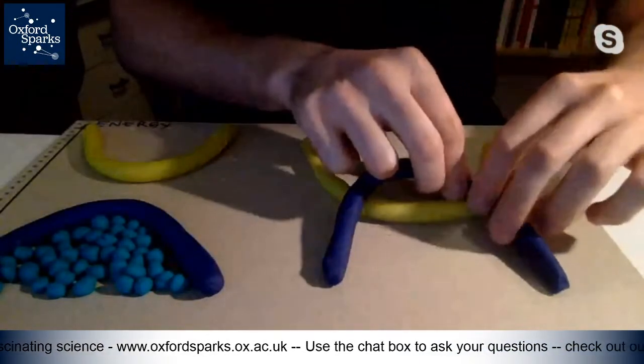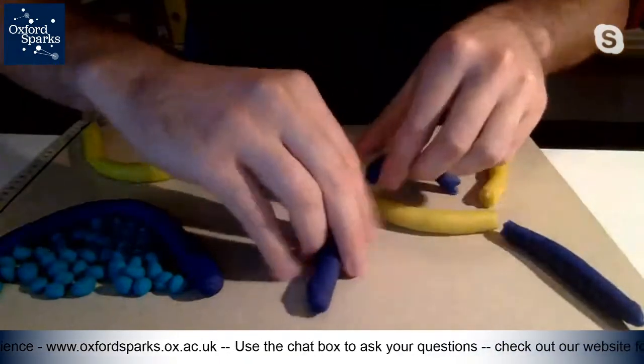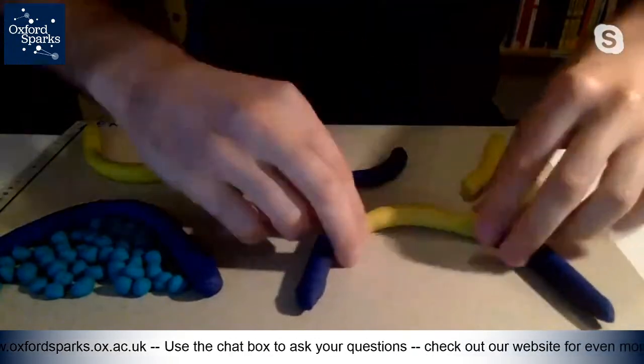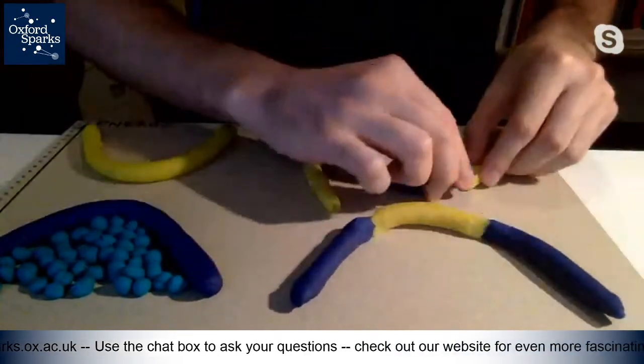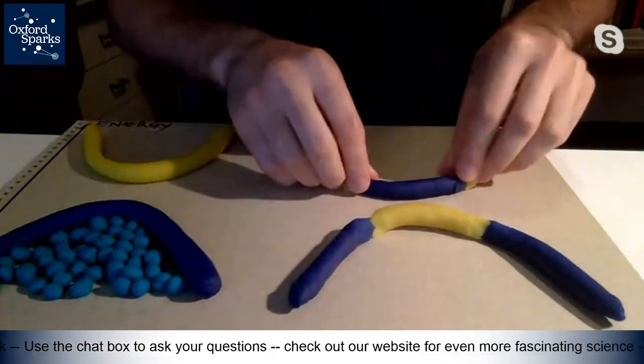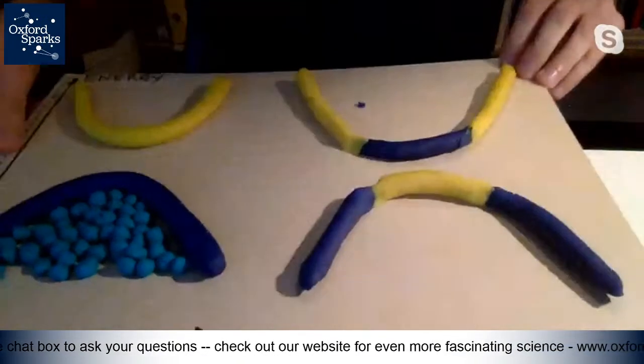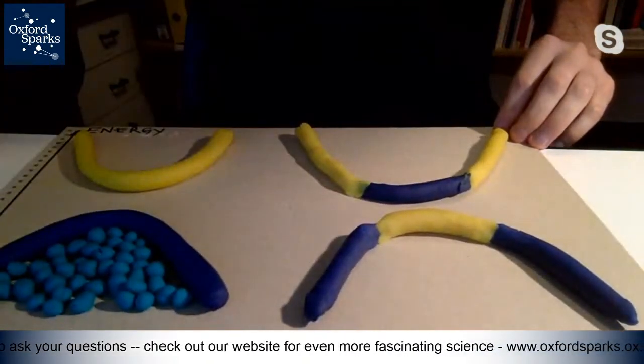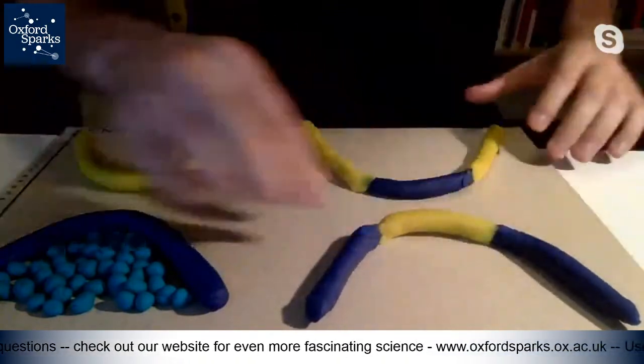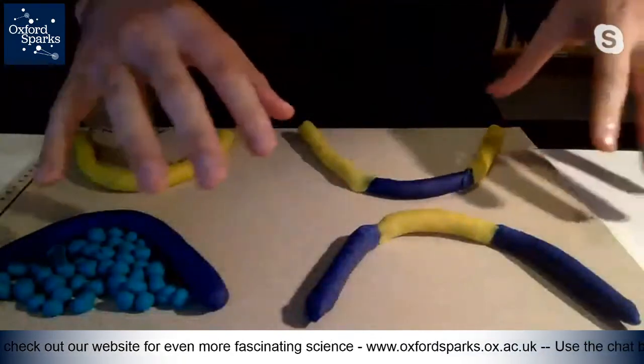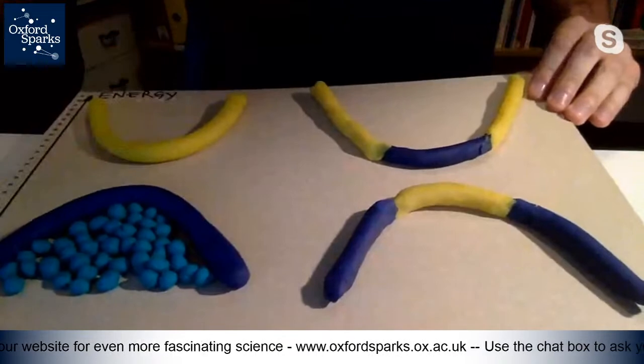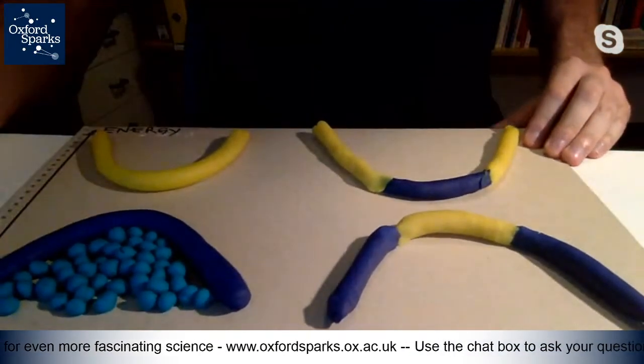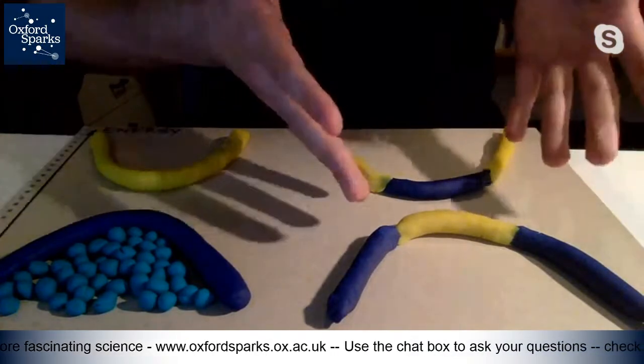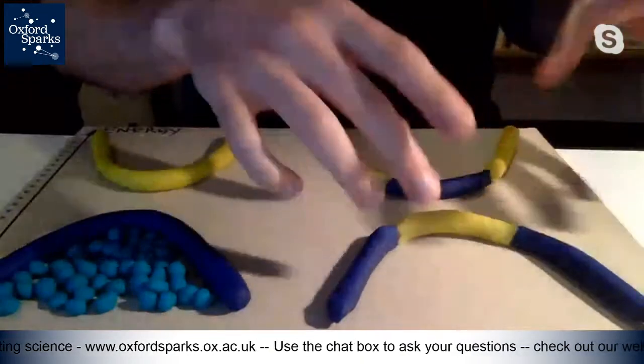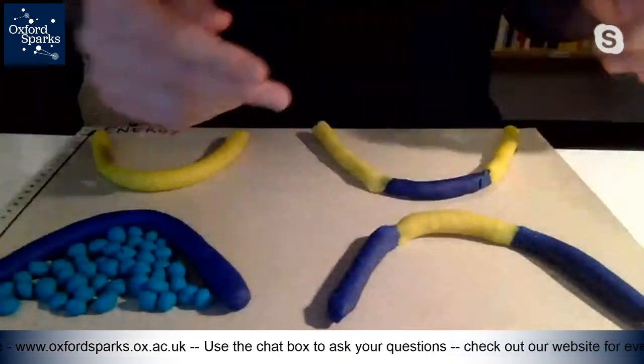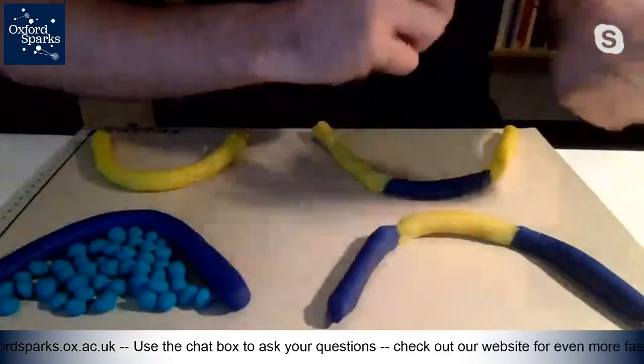But what happens actually is that because of the interaction, they form a different type of structure that looks like this. So we see that there is a change in color here. We have a part of the blue that goes to the yellow and vice versa. And we can see, so this is a different topological structure because we have a different occupation or different geometry of the band structure. So this is what characterizes a topological insulator. It has a different structure of the bands, which is called the band inversion, because we have inverted the bands.